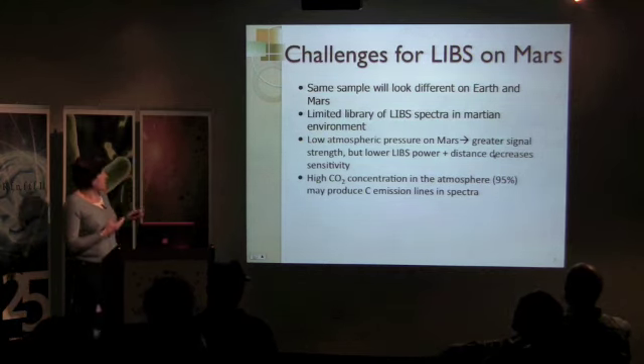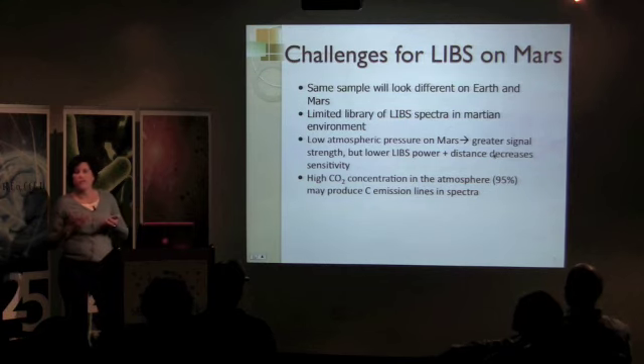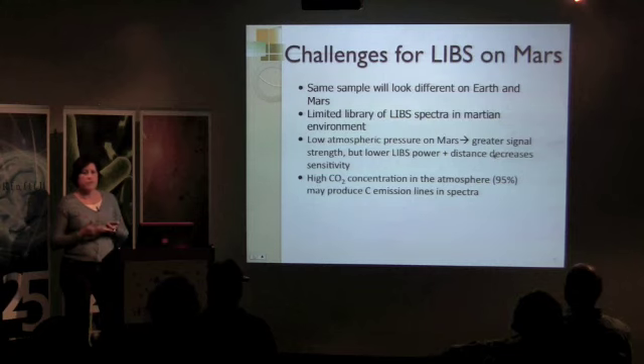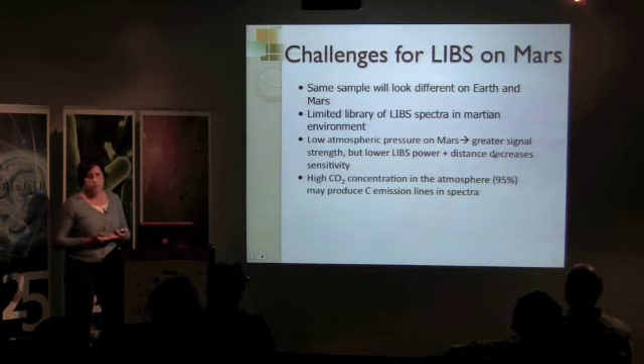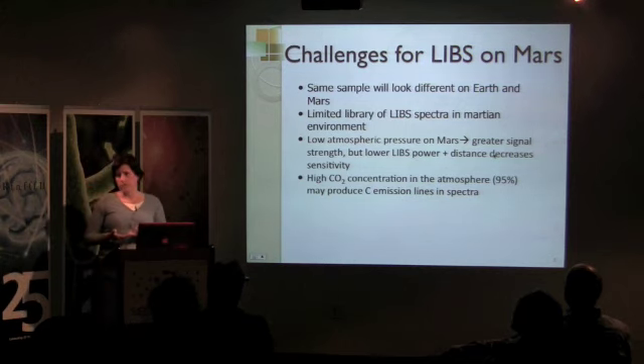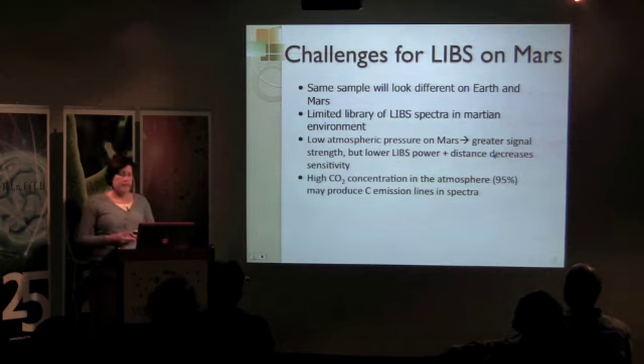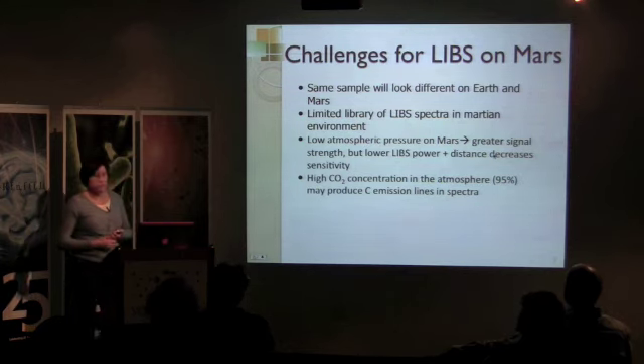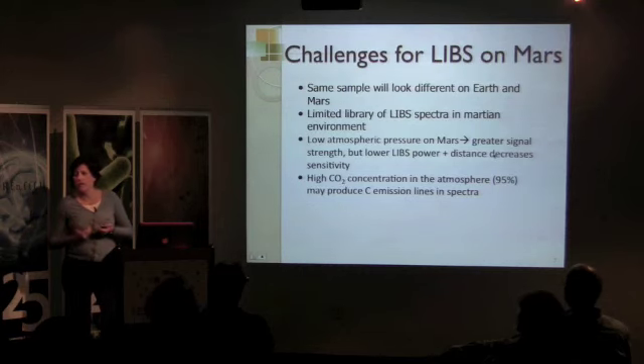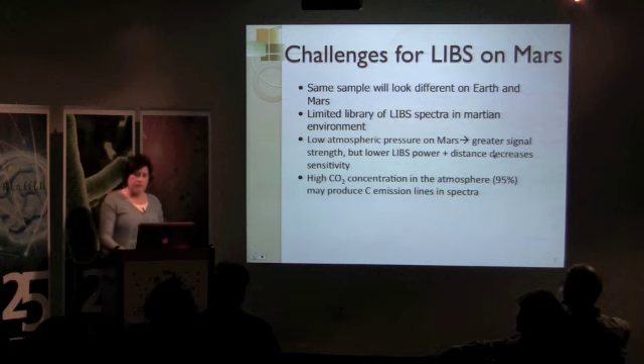And because there's low atmospheric pressure on Mars, that means there will be less interference with the laser signal. So there might be greater signal strength. But because we're dealing with a small portable payload instrument, we have much smaller power than you might use in the laboratory, and therefore that will decrease sensitivity. So these are competing effects. And finally, the high CO2 concentration in the Martian atmosphere may interfere with emission lines, especially when we're trying to detect carbon. So these are all challenges we're trying to address beforehand.